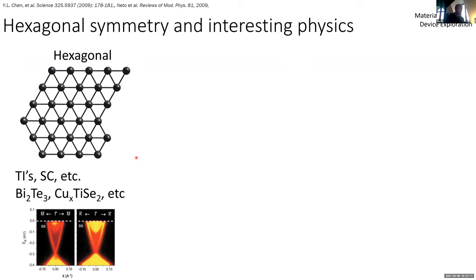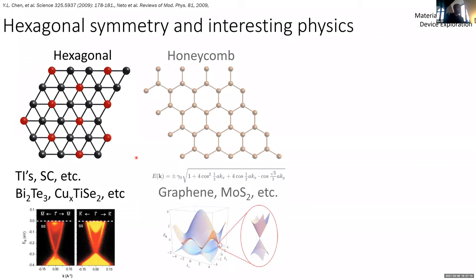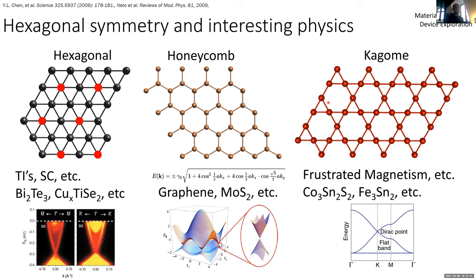So an interesting way to think about the classic hexagonal net is in terms of masking certain atoms. If you mask a certain arrangement of atoms in the hexagonal net, you can end up with a honeycomb, which of course is graphene, the prototypical Dirac semimetal. MoS2 and other layered chalcogenides have the same type of structure and, again, interesting properties. And if you mask a different set of atoms in the hexagonal net, you can end up with the famous Kagome net, which back in the day when we started looking at this was mostly known for potentially hosting frustrated magnetism, the iridates and things like that. Again, cobalt tin sulfide, iron three tin, these are also in the Kagome family. So these are interesting places to look for interesting physics.